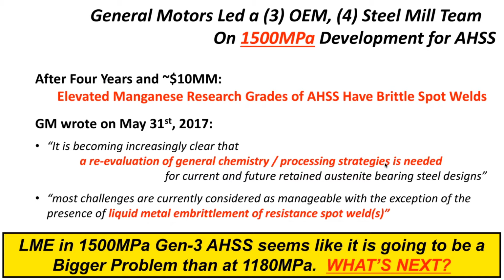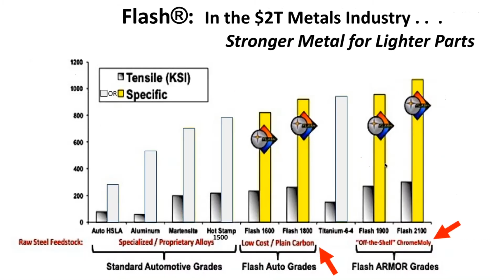Well, flash is dealing in a $2 trillion metals industry, as we all are, and this is a chart on specific strength. If you look at the far left, second column in, you can talk about aluminum, and aluminum at 50 KSI divided by its 0.1 pounds per cubic inch has a specific strength of about 500. So when the Ford F-150 commercials come on and they talk about aluminum stronger than high-strength steel, technically they're correct, but HSLA really isn't high strength, I don't think, by any stretch of the imagination anymore.